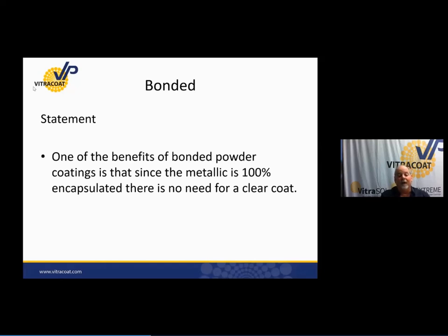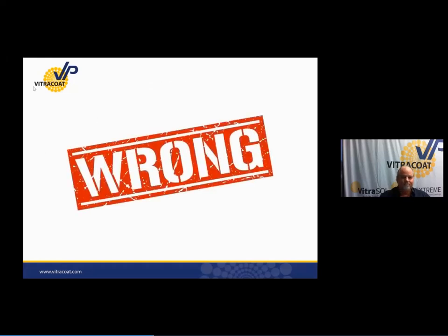Bonded. One of the benefits of bonded powder, which is a metallic coating, is that since the metallic is 100% encapsulated, there's no need for a clear coat. So one of the benefits of using a bonded technology is that the metallic in that formula is 100% encapsulated because of the bonding process, and therefore clear coat's not required. Wrong again.